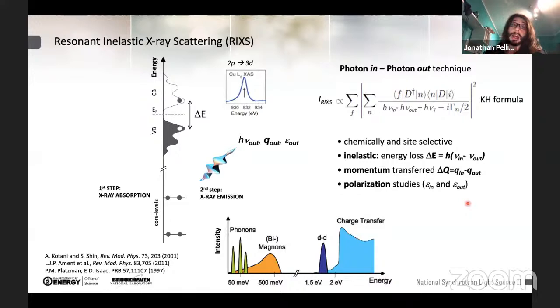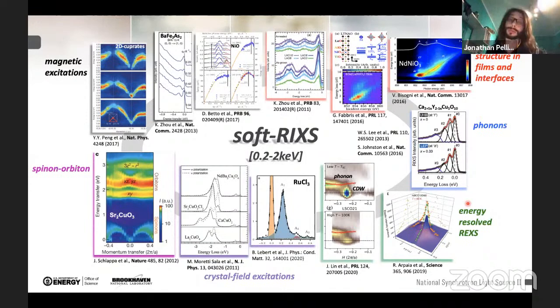Just to give you a few examples of what RIXS can do and what RIXS has done in the past, I'm showing here a few examples of what we call soft X-ray RIXS, which implies an incident energy between 200 eV and 2 keV. And these comprehend essentially all the 3d transition metals. So RIXS has been used to investigate the spin excitation in two-dimensional cuprates, iron-based superconductors, and nickel oxide. It has been used to study the electronic structure of different thin films, for example, in the nickelates. There has been work also on LAO-STO systems in the past. RIXS has been used to investigate phonon excitation and the connected electron-phonon coupling in low-dimensional systems and two-dimensional cuprates, and also to study the effect of charge density waves on phonon excitations.